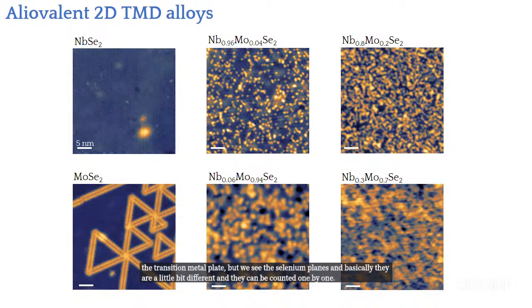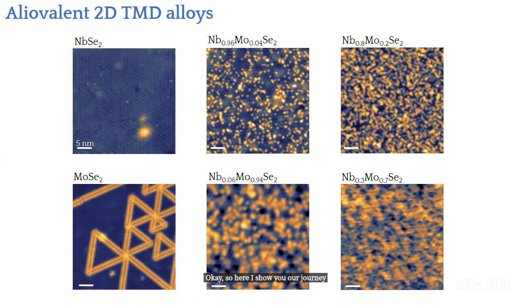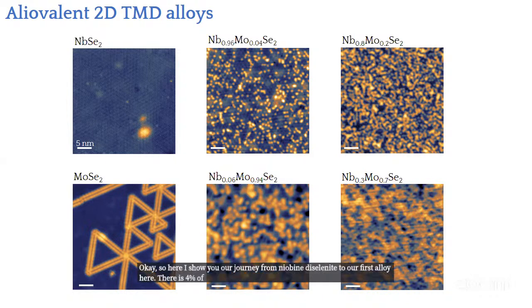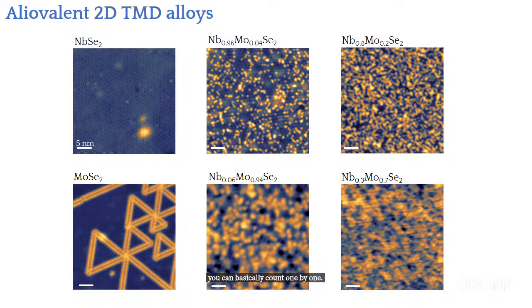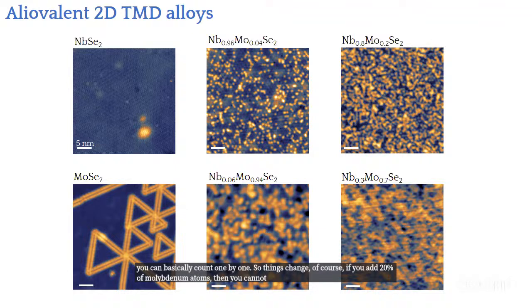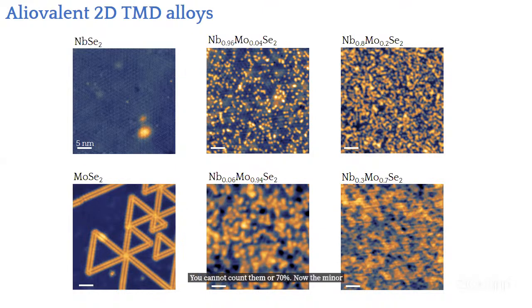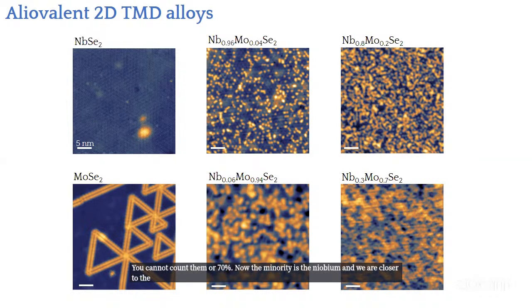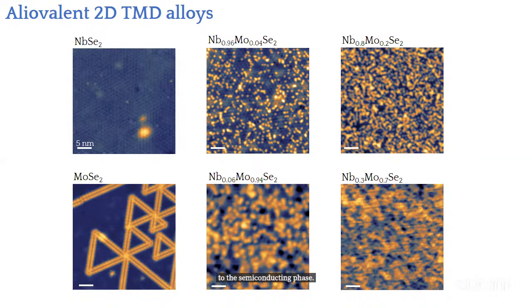Okay, so here I show you our journey from niobium diselenide to our first alloy. Here there is 4% of molybdenum atoms. So with 4%, you can count one by one. Things change, of course, if you add 20% of molybdenum atoms, or 70%, then you cannot count them. Now the minority is the niobium, and we are closer to the semiconducting phase. Here, it's close to molybdenum with just 6% of niobium, and now you can count individual niobium atoms, and this is the end of the journey with MoSe2.